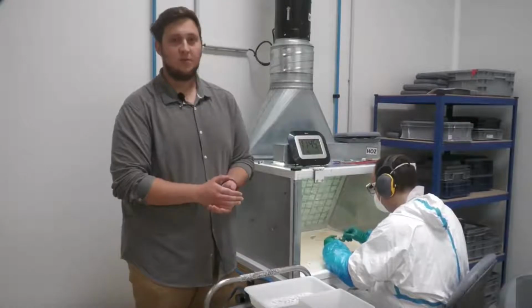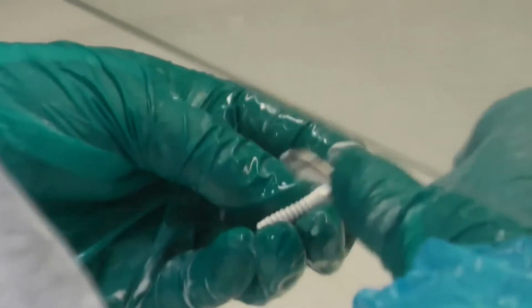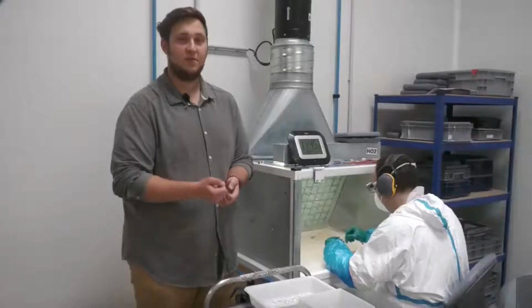Under the extractor hood, we start by cleaning around the pieces before delicately removing them from the support. Afterwards, the pieces are thoroughly cleaned with the nozzle, but for more complex pieces, it is sometimes necessary to perform an ultrasound bath to ensure that all the unpolymerized material has been removed. It is important that all the unpolymerized material has been removed from the pieces before proceeding to the firing stage.